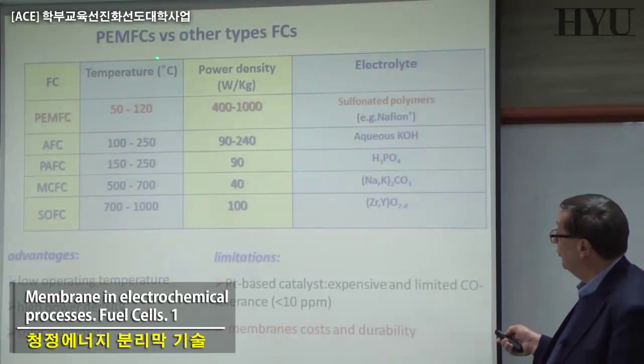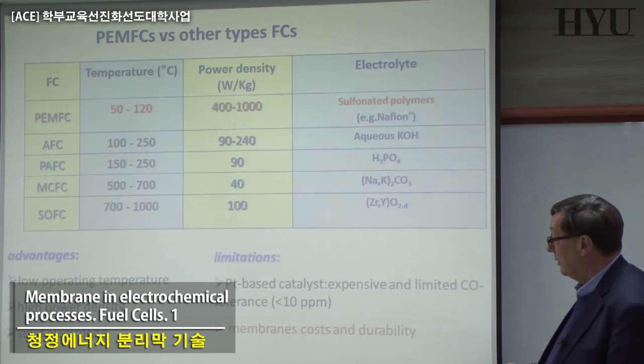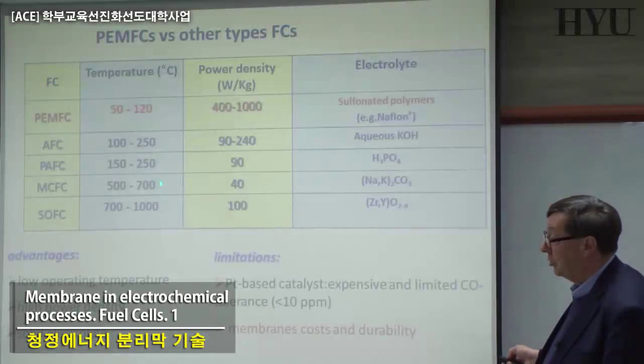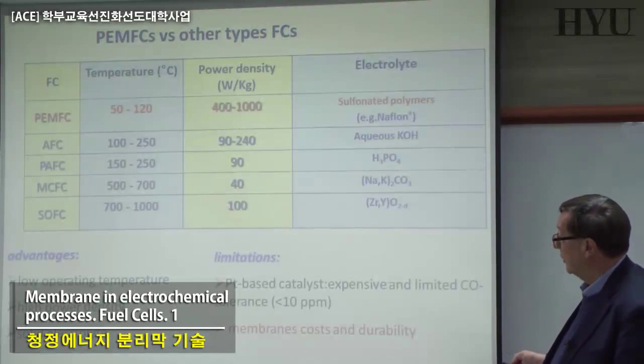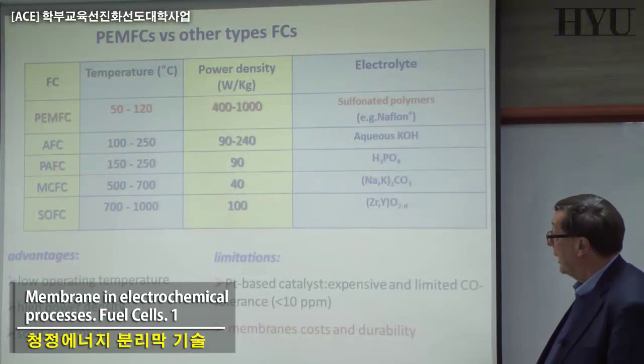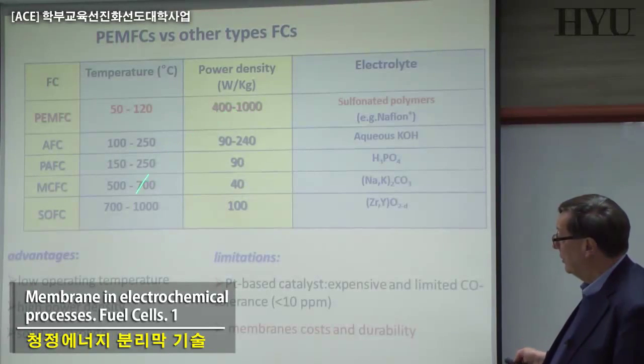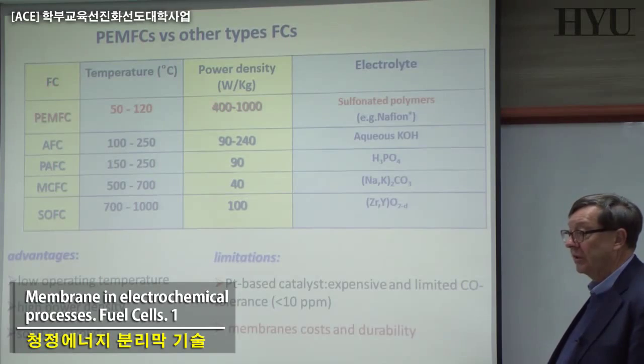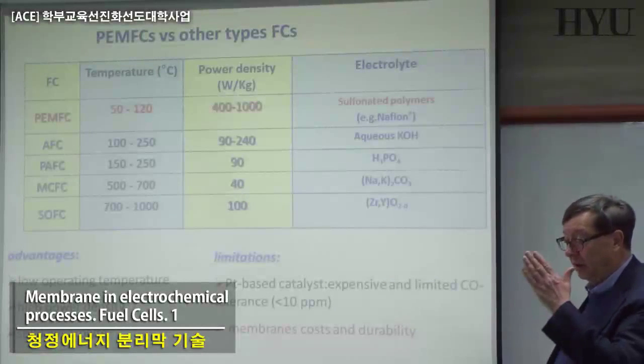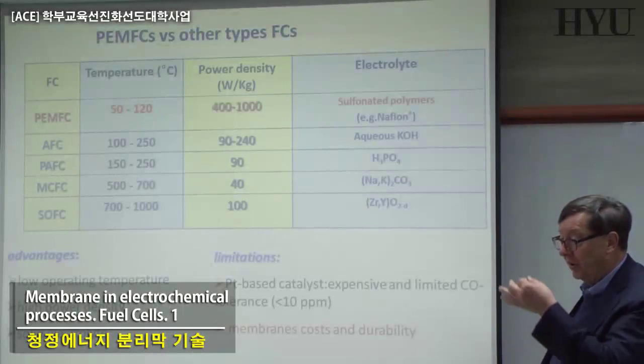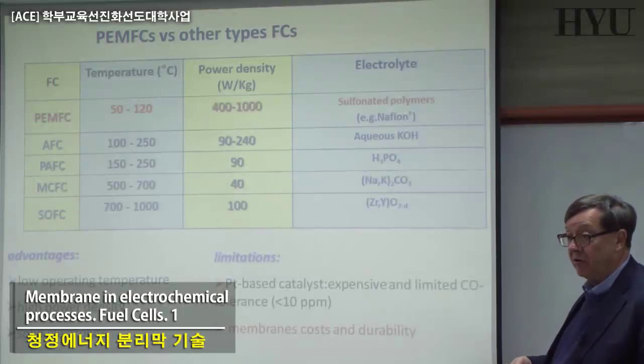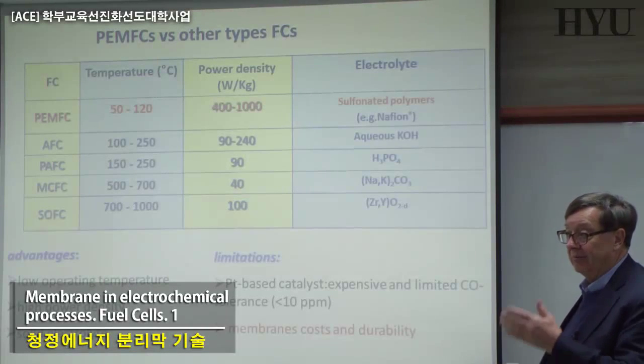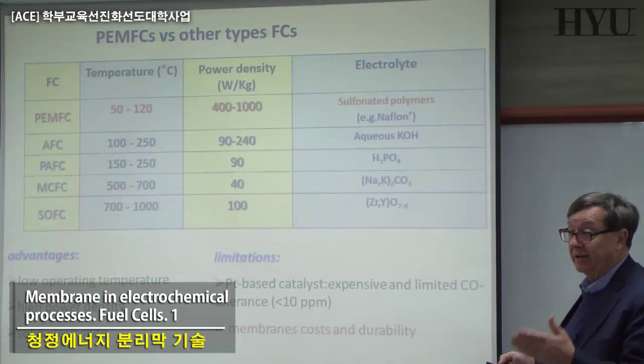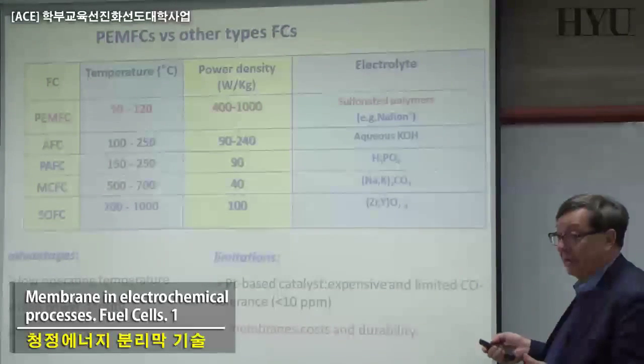The advantages of this kind of membrane are that they operate at relatively lower temperature than all the others, which is quite useful. They have the highest power density, and they use a solid electrolyte, which is very easy to form in a very thin layer. For all the membranes we have been studying until now, the highest thickness was 100 microns, but it can be 20, 10.